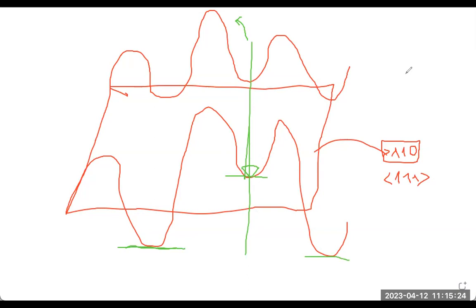You just increase stress again and again constantly till maybe 400 megapascals, 500 megapascals, and with thermal activation, you firstly activate the middle part of this screw dislocation. So this middle part will go to the top.